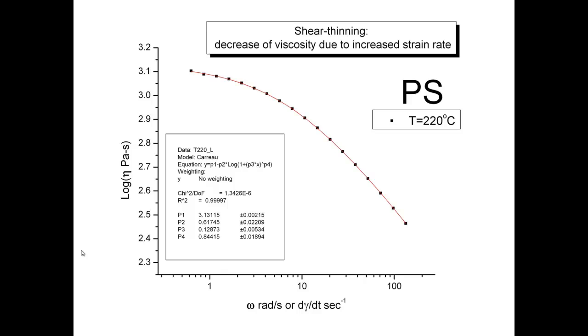Now let me introduce you to two modes of processing which are currently being used, especially the one illustrated in this figure called shear thinning, in processing. For processing melts, the increase of the strain rate, the increase of the speed at which we make melts flow through capillaries or through gaps in mold injection molds, for instance, is known to create a decrease of viscosity, as illustrated in this figure.